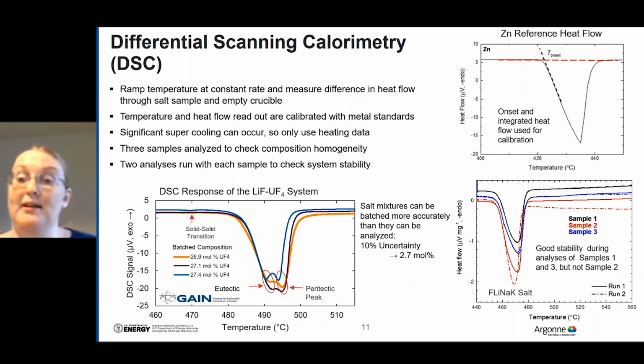And you can see an example of why that's important in the bottom figure on the right here, where we measured 3 samples of FLiNaK, and you can see their onset temperatures agree really well, indicating that the batch was homogeneous. But in sample 2, the dotted line and the solid line do not fall directly on top of each other, indicating that something occurred during the measurement of sample 2, which caused the system to be unstable. So we would discard those data for future use.